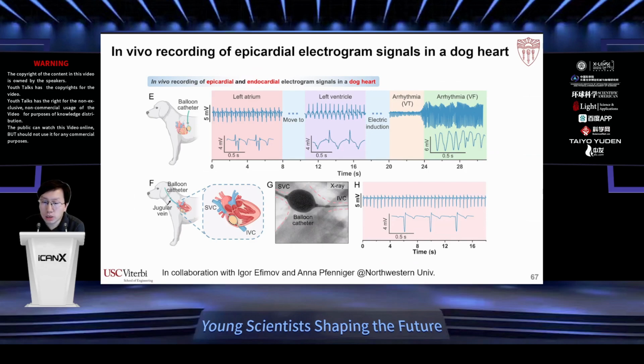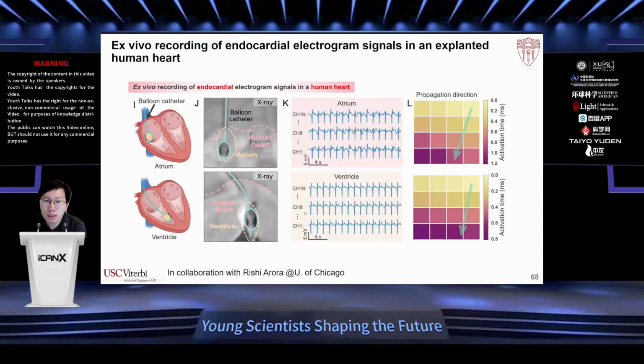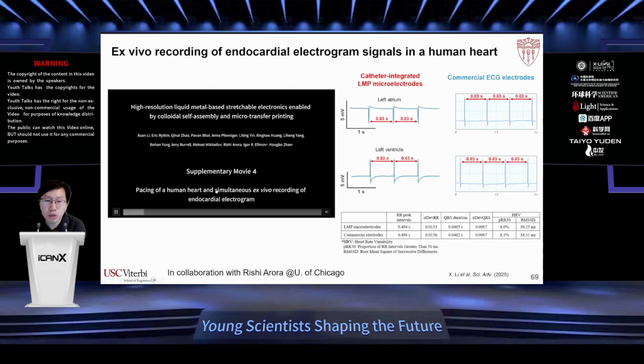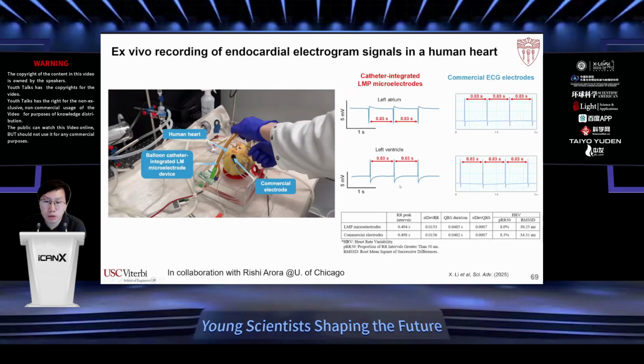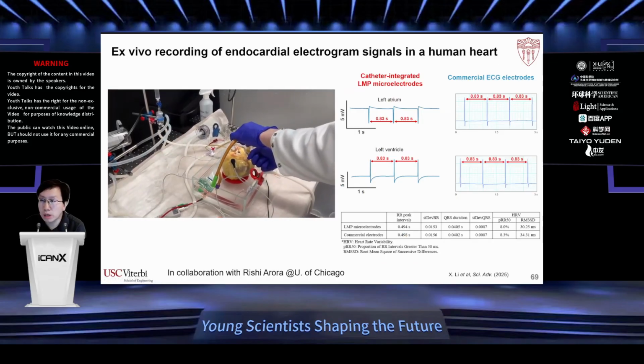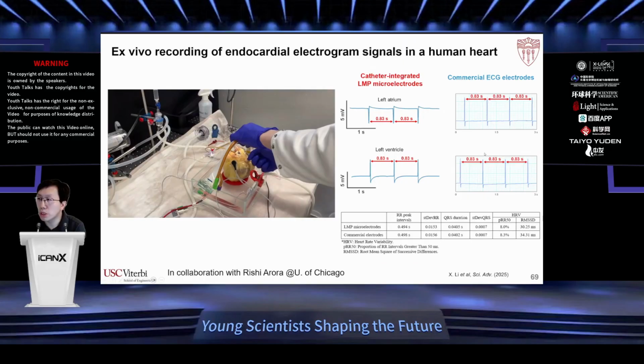So in this case, we can measure the electrogram signals from the endocardial heart wall, which matches very well with commercial electrodes. And in this case, we tested endocardial electrogram recording in an explanted human heart, and again, we can not only measure the endocardial electrograms with high resolution, we can also map the propagation direction of these signals because of the large arrays we have. And this is a video showing we are doing endocardial electrogram recording in a beating human heart. And the key signal characteristics match very well with what we can measure using commercial ECG electrodes from the epicardial surface.